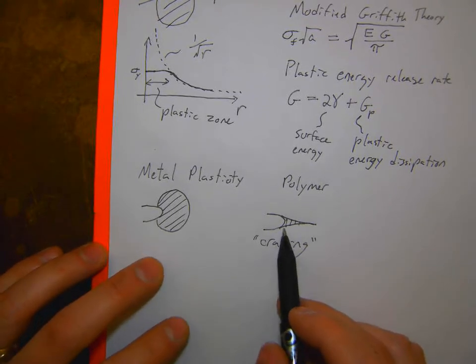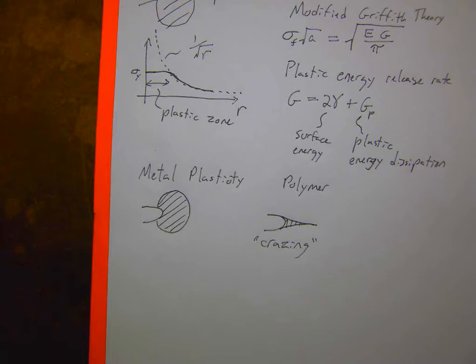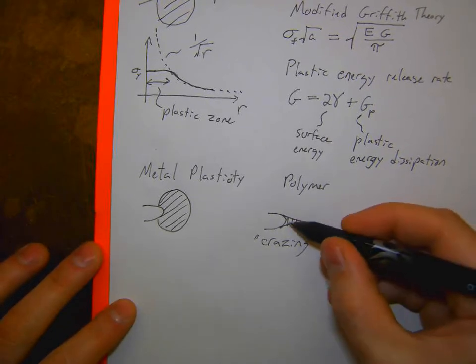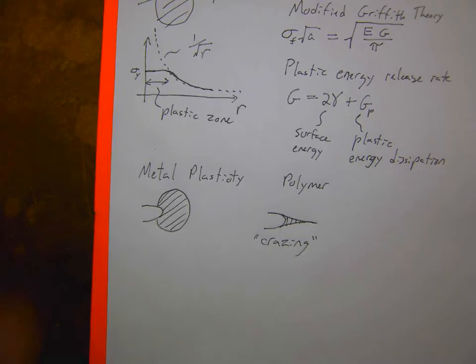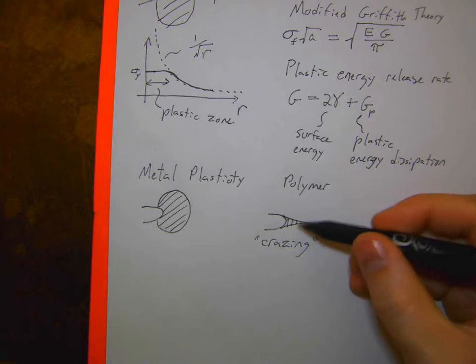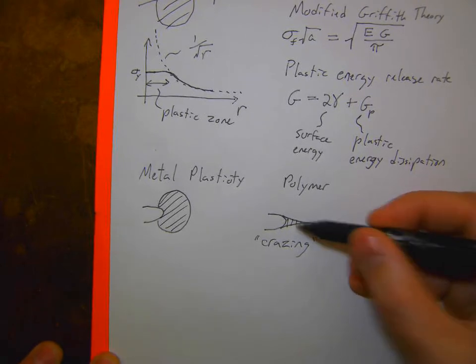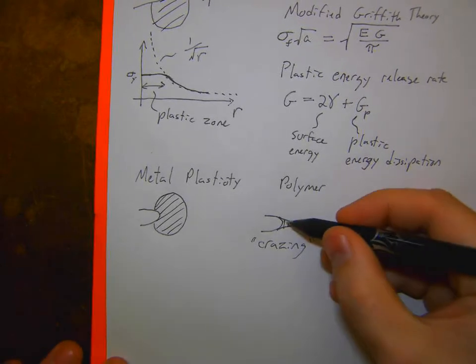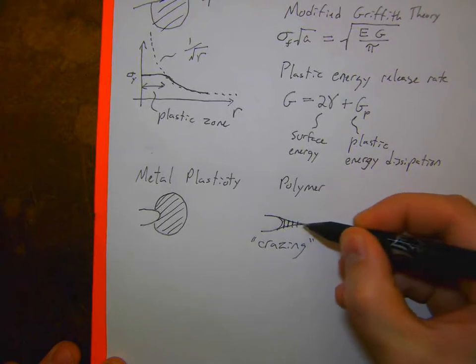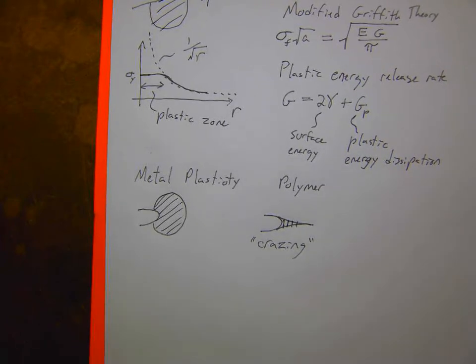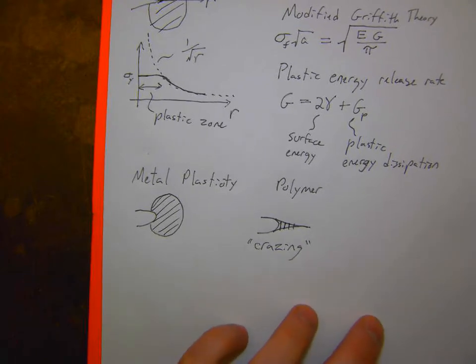Around a polymer, because you have this sort of molecular spaghetti, what actually happens in that plastic zone is the molecules will get stretched out, and you'll see molecules getting stretched out across the tip of the crack. And so you get this crazing phenomenon, where you have long strands of polymer getting stretched across. They have some good illustrations of that happening in the Meyers and Chawla book.